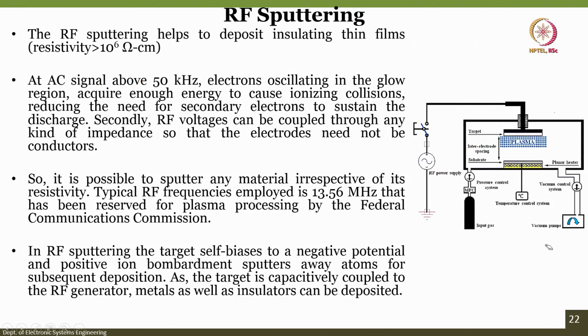Now, with RF frequency, that means an AC signal of about 50 kilohertz, electrons oscillating in the glow region acquire enough energy to cause ionizing collisions, reducing the need for secondary electrons to sustain the discharge. Secondly, the RF voltage can be coupled through any kind of impedance. The electrodes need not be conductors. So, this is the advantage, because the RF voltages can couple through any kind of impedance, it is possible to sputter any material irrespective of its resistivity.